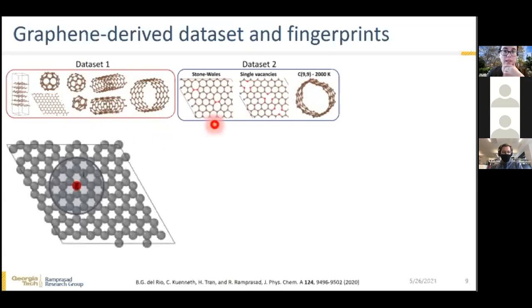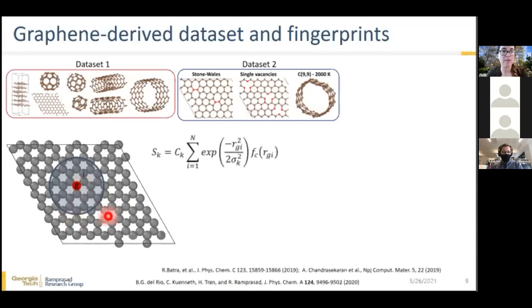And to fingerprint all these configurations, we use the group's previously developed fingerprint expressions, but instead of fingerprinting the environment of each grid point, we center the fingerprints at each atom. As such, if we want to create the fingerprints describing the atomic environment of atom G here, we can create a scalar fingerprint, which takes the form of a Gaussian function, which depends on the distance between the atom G and its neighbor I, and has a width, which is sigma k, which is a variable that we can specify.